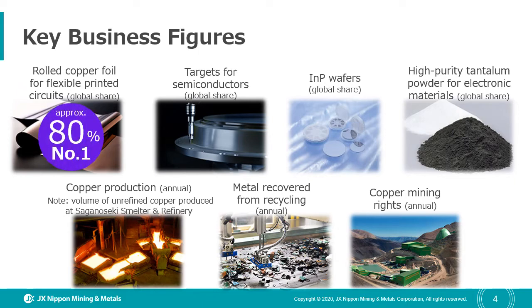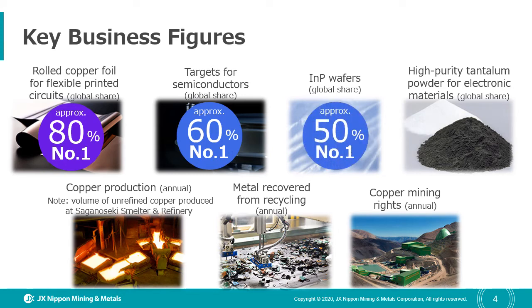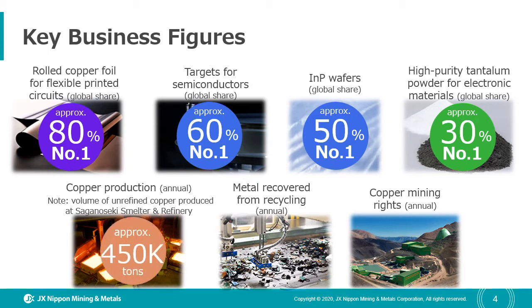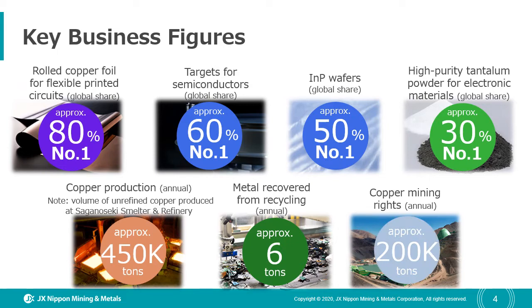JX has a global market share of 80% for rolled copper foil for flexible printed circuits, 60% for sputtering targets for semiconductors, 50% for indium phosphide wafers, and 30% for high-purity tantalum powder. JX produces 450,000 tons of copper per year and recovers 6 tons of rare metals per year from recycling. JX owns copper mining rights for 200,000 tons per year.